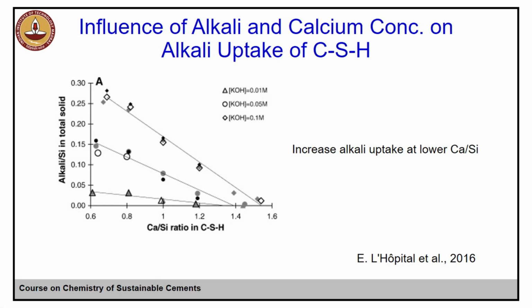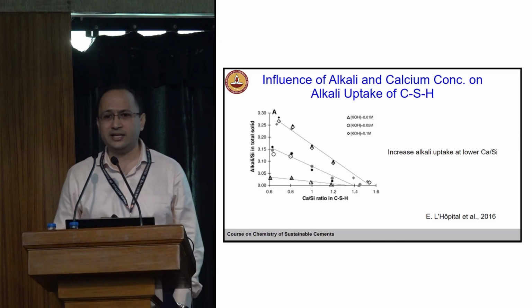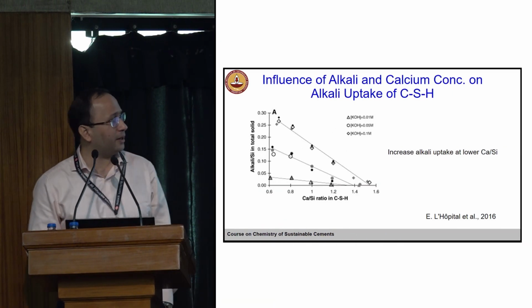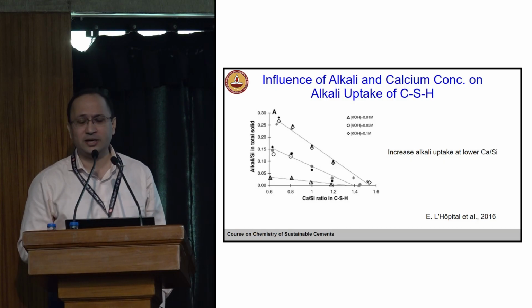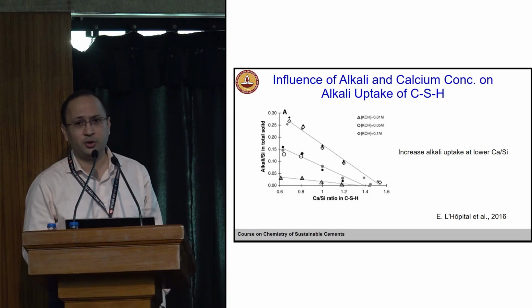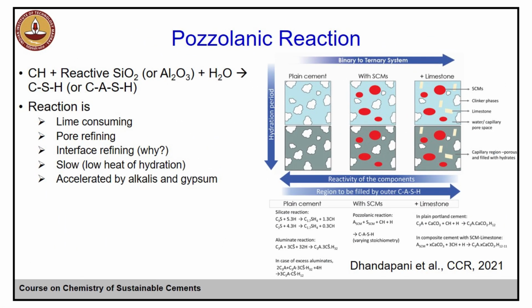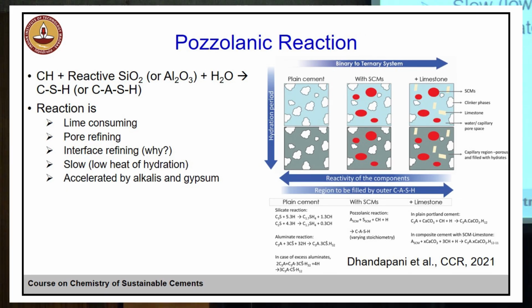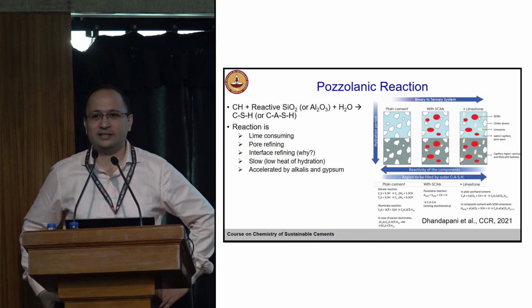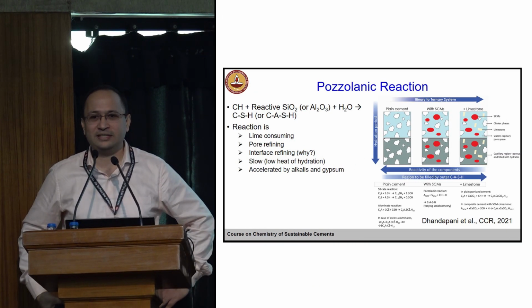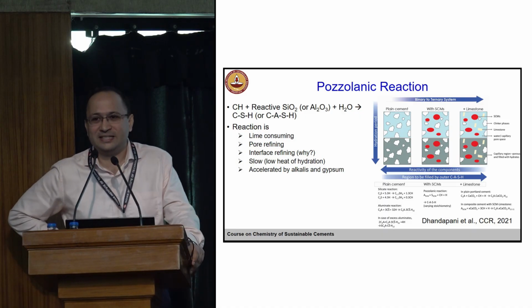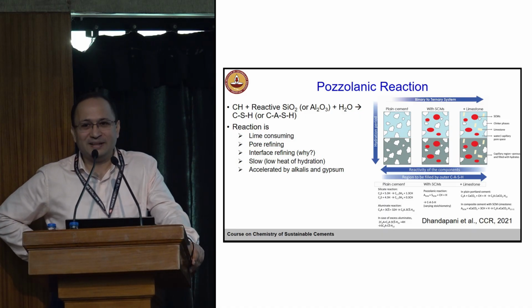Another example showing you here, again, increased alkali uptake at lower calcium. So it's pretty well understood how the alkali binding changes as C to S ratio is reduced with the introduction of SCMs. Now we are going to talk about the so-called bad guy. It may not be bad, because it buffers the solution and provides a passive layer on reinforcement, which is very good to improve the corrosion resistance. This is calcium hydroxide.